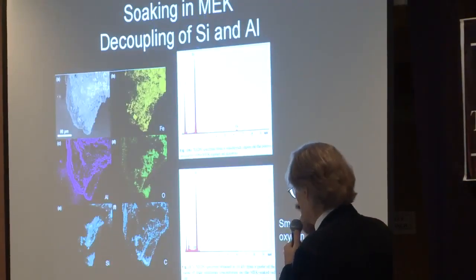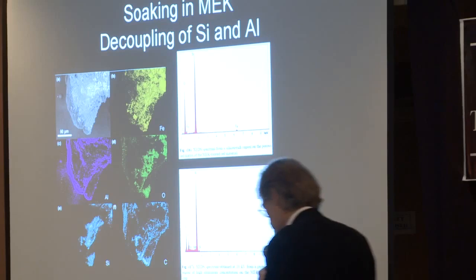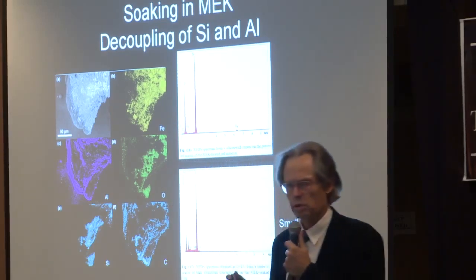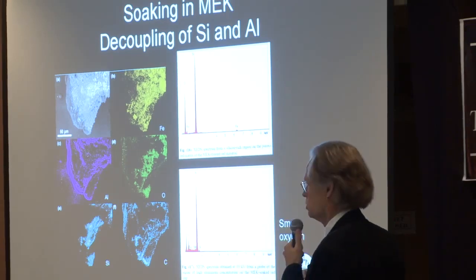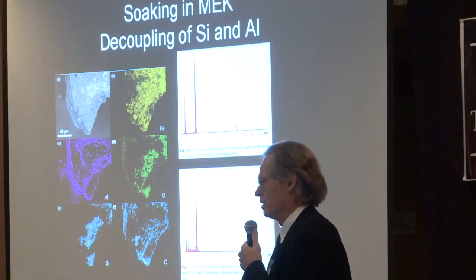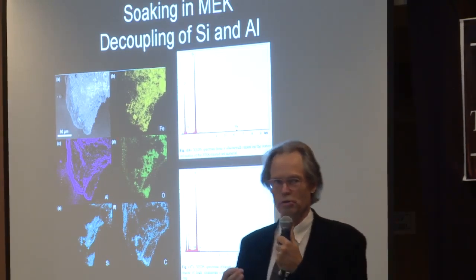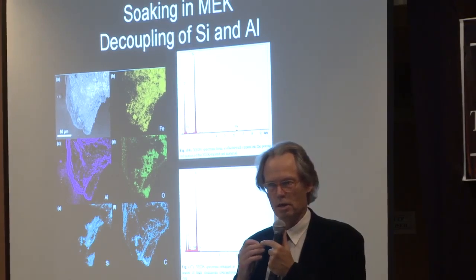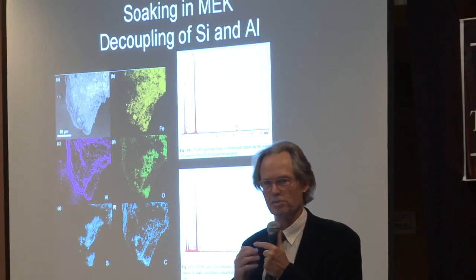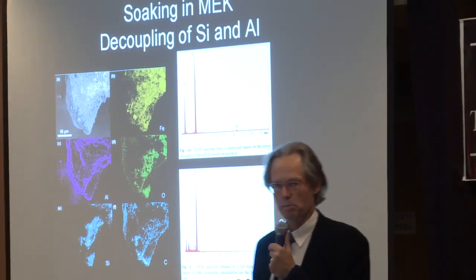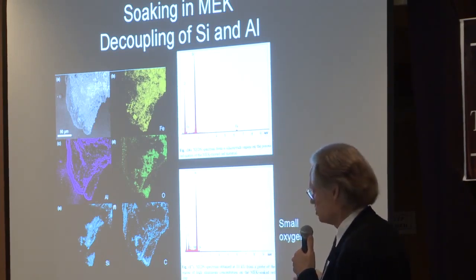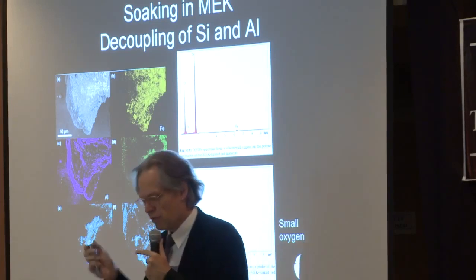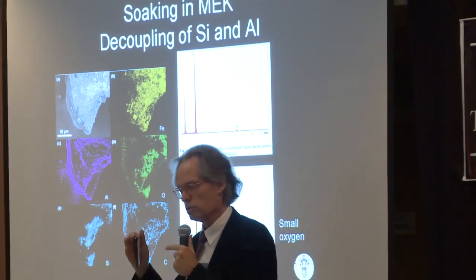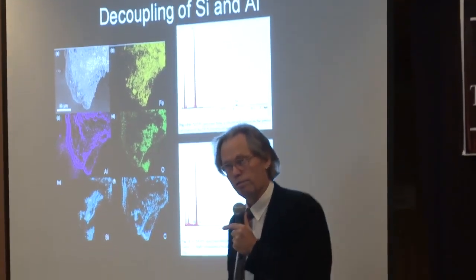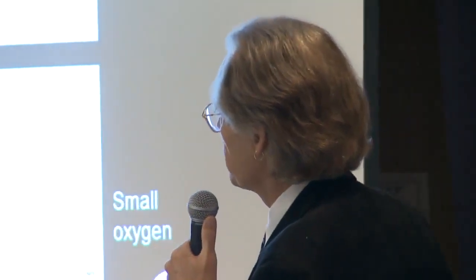But we did an experiment where we dropped 1 chip at a time into an organic solvent called methyl ethyl ketone. This, ladies, is almost the same as acetone, which you all know for removing your nail polish, right? So let's say it's acetone. It would work the same, but we use methyl ethyl ketone because it has a higher boiling point. It's easier to work with. Now, if you drop one of these chips into methyl ethyl ketone, the red phase swells like a sponge. Like if you put a dry sponge in water, it swells almost 6 times.